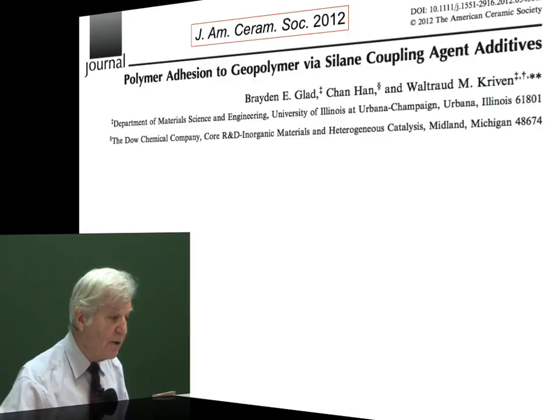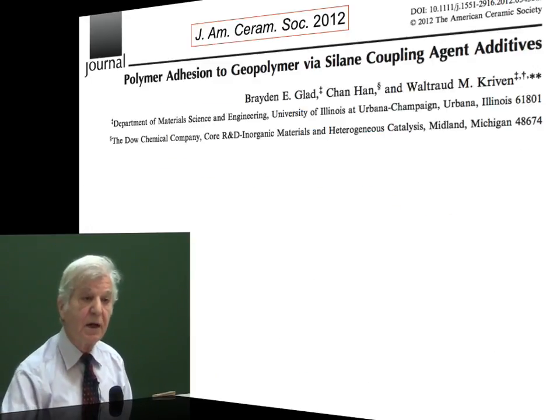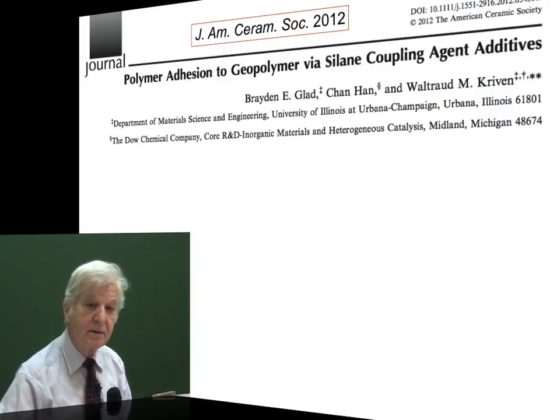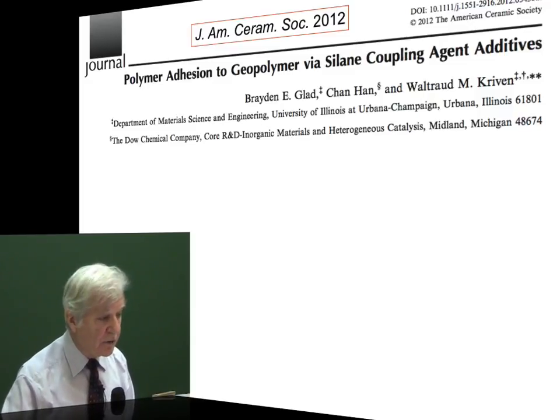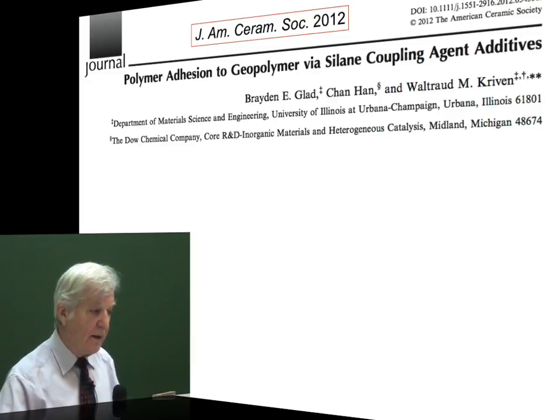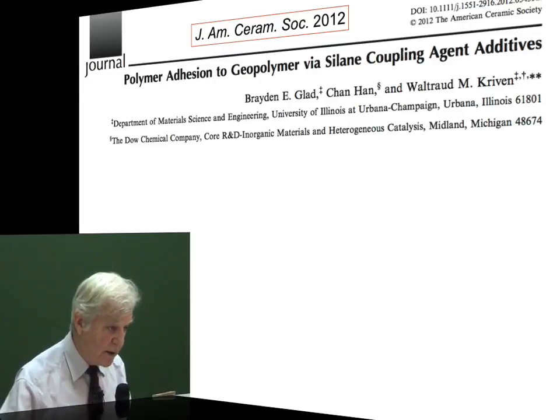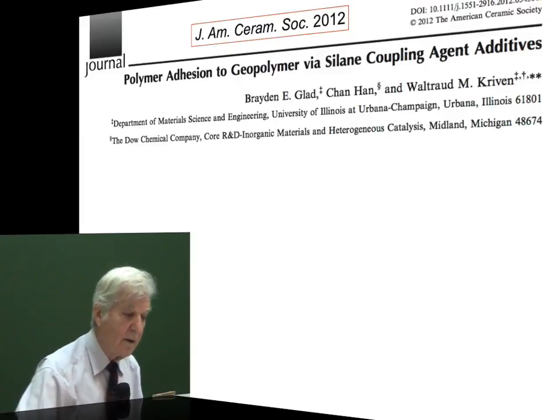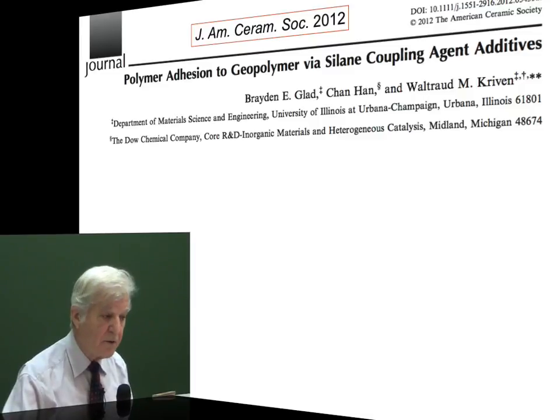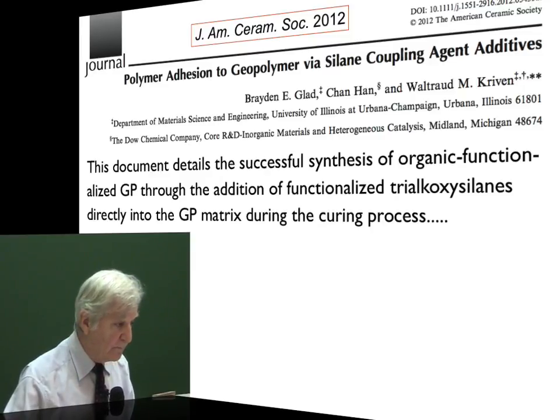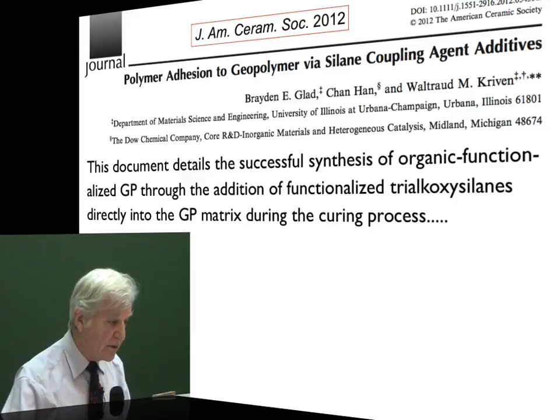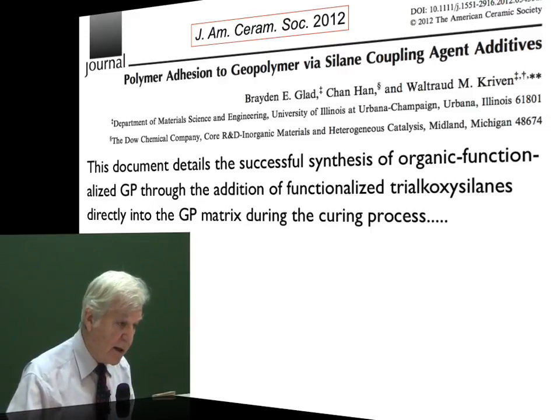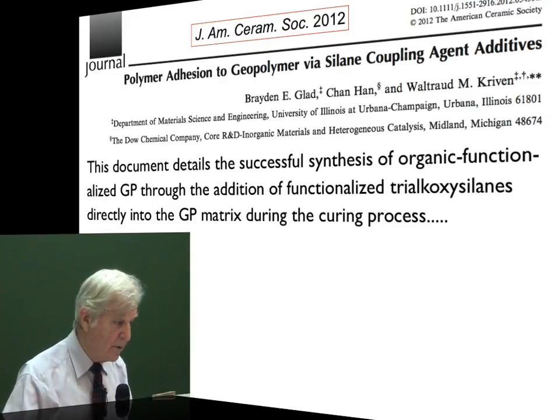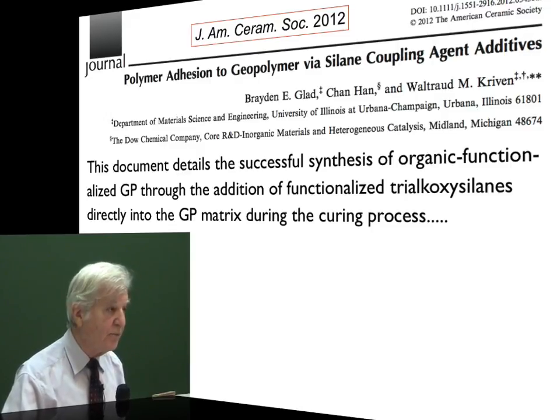We are still working with adhesion, but this time we will include organic-based systems. Here, this is an organic mineral, a silane in the system as an additive, and this has been done by the team at Urbana-Champaign, Illinois University, and the Dow Chemical Company. This paper details the successful synthesis of organic functionalized geopolymer through the addition of functionalized trialkoxysilanes directly into the geopolymer matrix during the curing process.